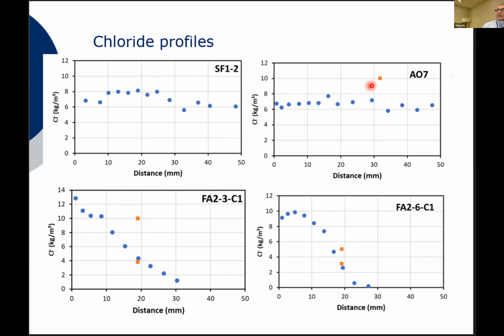Whereas for this other sample, this is a thicker concrete cover, and you can see that right at the rebar trace, the concentration is larger than that observed from the core.